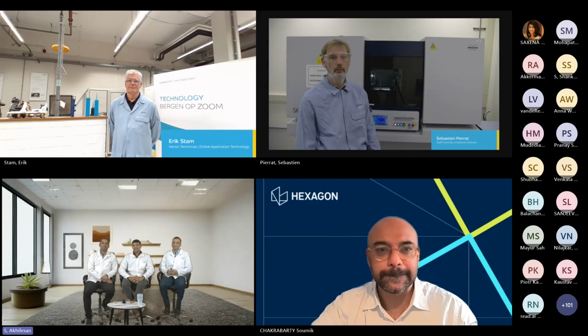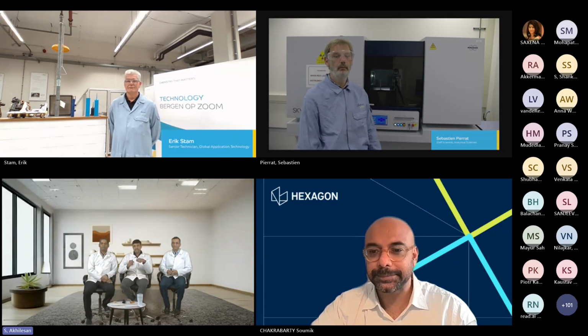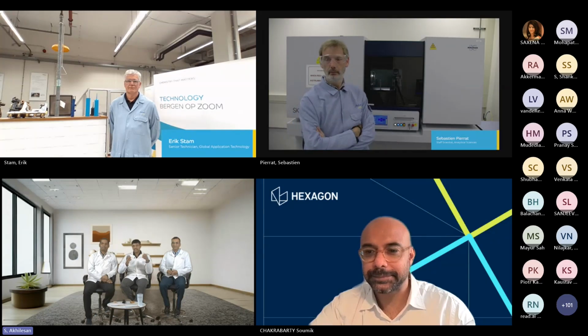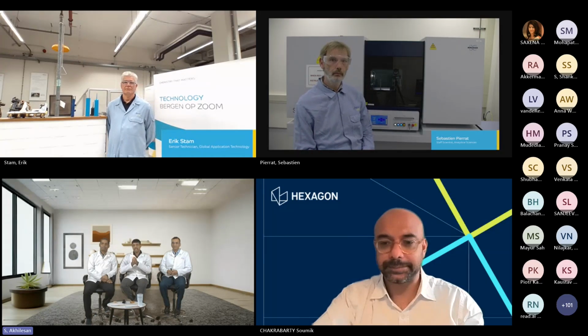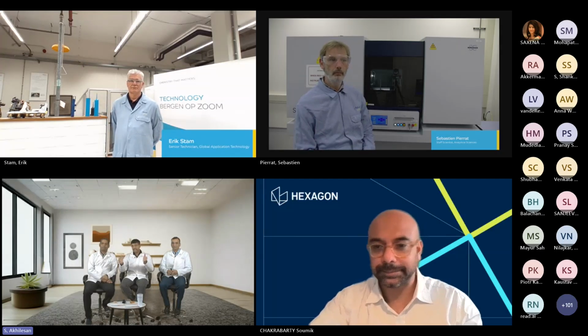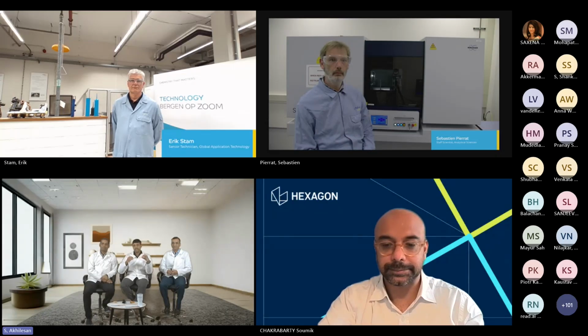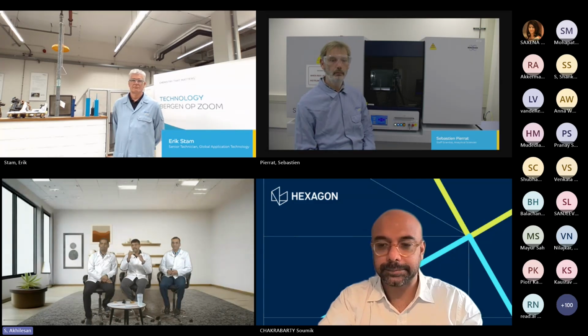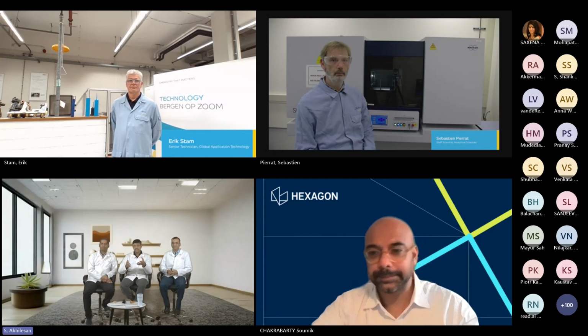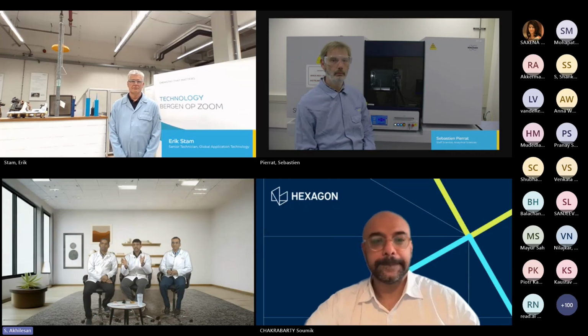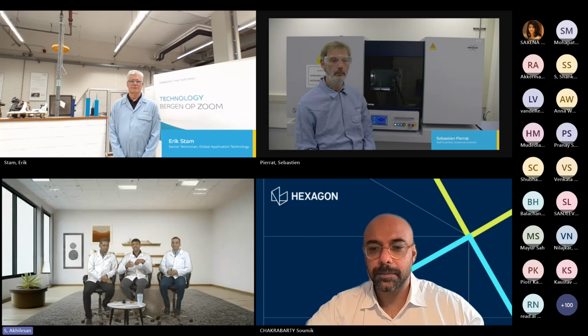Thanks, Soumik. Yeah, so that's a very good question. As you can imagine, when you injection mold a tensile specimen, a directly injection molded tensile specimen, you can establish that the fiber orientations get really well aligned. Whereas in a shear plaque, it is a much wider width of flow, so you do not expect such a well alignment of fibers. And also the processing conditions do vary, the shear experience does vary. So our experience has been that in directly injection molded tensile specimens, you get much higher alignment than even the 0-degree cut specimens. So in real world scenarios, I would say 0 is your best performance measure, and 90-degree would be your worst performance measure for a tensile behavior. And directly injection molded is even overestimating it compared to what is possible in the real world. That's how I would put it. I hope that answered the question.